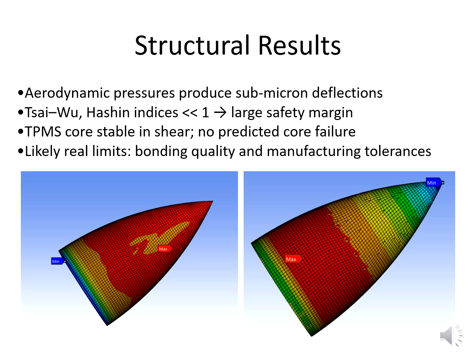Across the load cases, the nose cone demonstrates extremely high stiffness relative to its mass and size. Under realistic aerodynamic pressures, deflections were extremely small. The composite face sheets showed failure indices far below unity for all Tsai-Wu and Hashin modes, indicating very large safety margin. The TPMS core itself remained within elastic limits and no core shear collapse was predicted. These results confirm that the sandwich architecture performs exceptionally well.